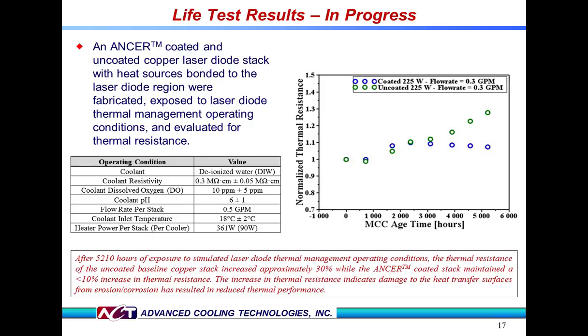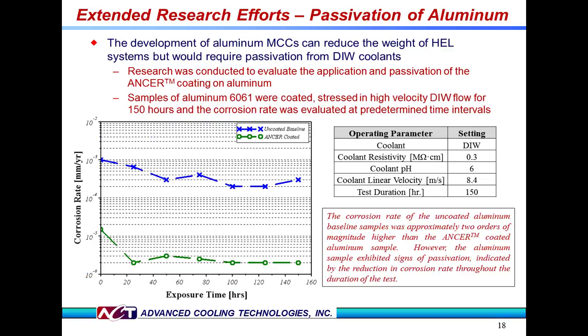We see for the first 3,000 hours or so, there is no meaningful change in normalized thermal resistance for either of the samples. However, at this 3,000 hour point, the thermal resistance of the baseline sample is starting to increase, while the ANCER-coated sample remains stable. The trend of increasing thermal resistance has continued in the baseline sample and suggests some degradation in the bare copper, likely caused by erosion-corrosion effects. During this time, the ANCER sample remains unchanged. We'll just have to wait and see if the trend continues, but at this point, ANCER is providing long-term corrosion-erosion protection.